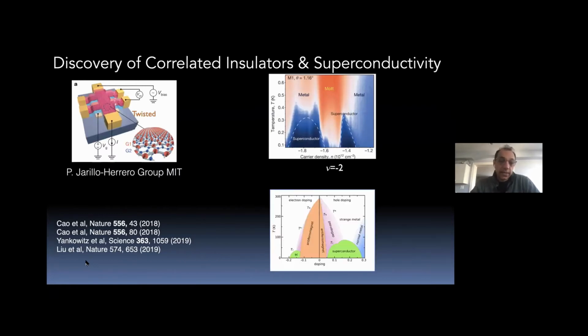Okay, so of course you heard in detail about the discovery of correlated insulators and superconductivity, and the impressionistic connection between the phase diagram of the system and that of strongly correlated systems like high Tc or heavy fermion superconductors. So this is all very nice, and superconductivity seems to come out of an insulating phase. But what is nice about this system is that the ability to control a lot of parameters in a chemically clean setting allows us to quantitatively measure correlations rather than just make an impressionistic comparison to a phase diagram. And this is the first part of my talk, which I'd like to show you.